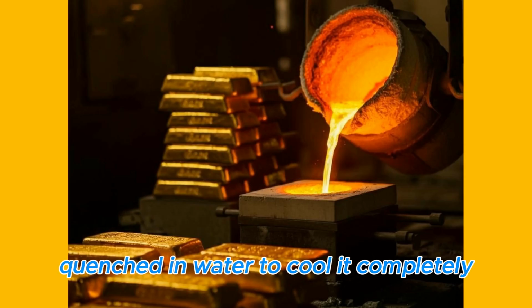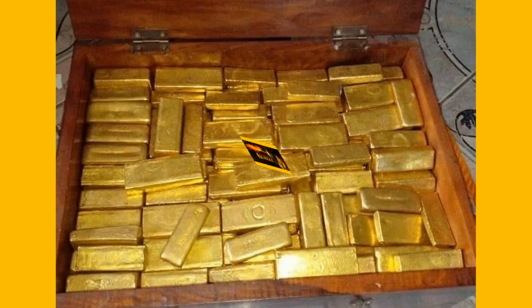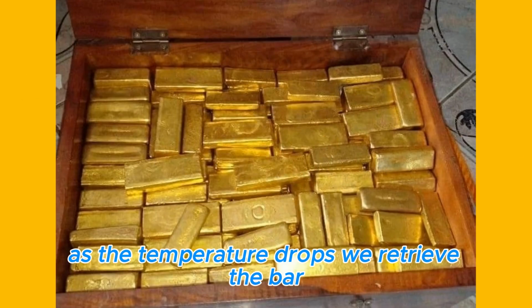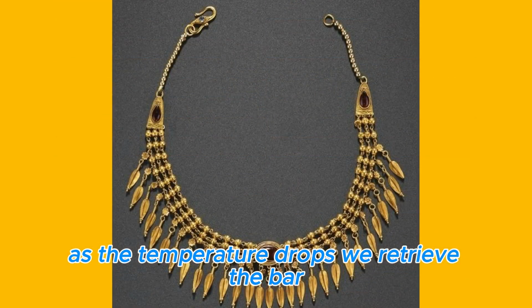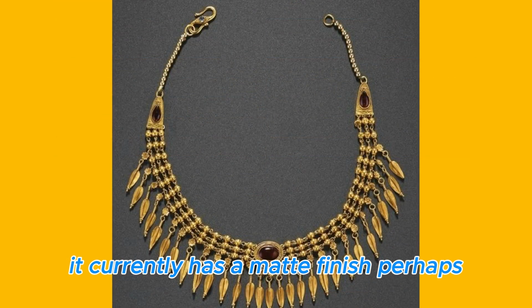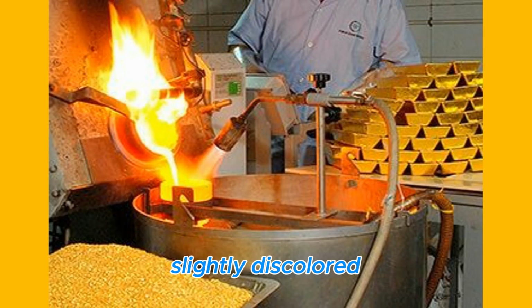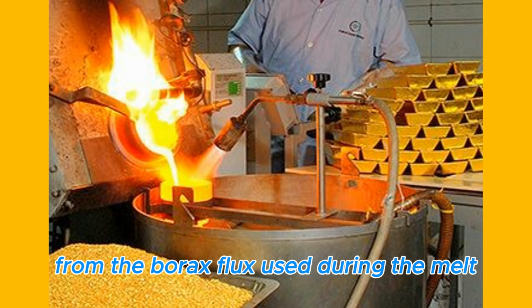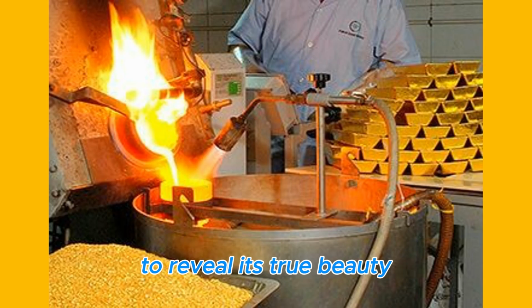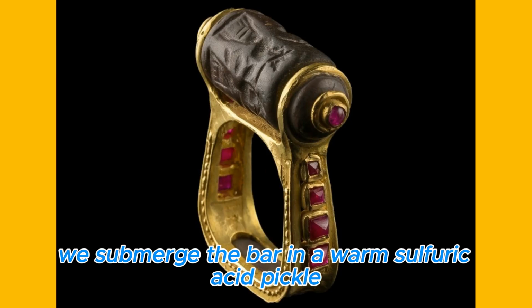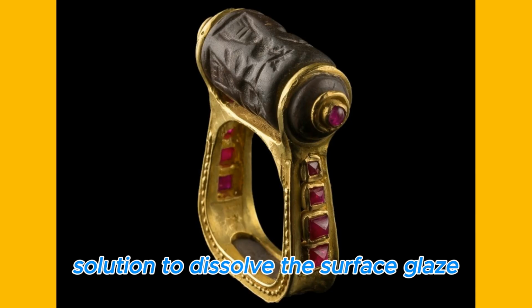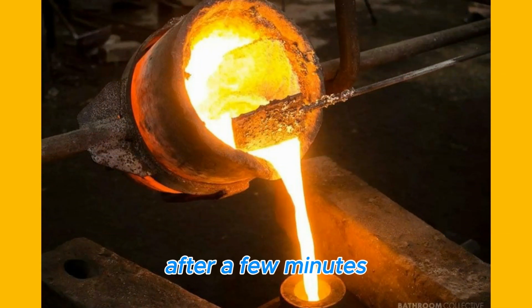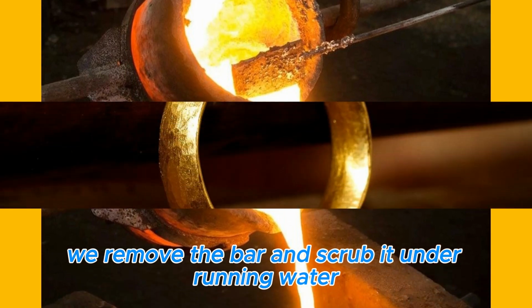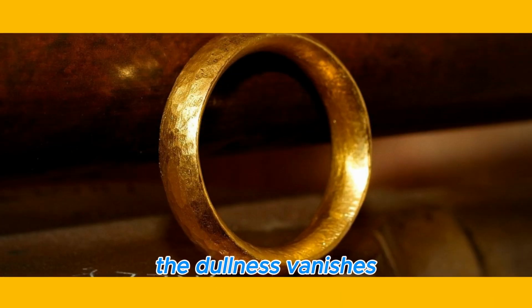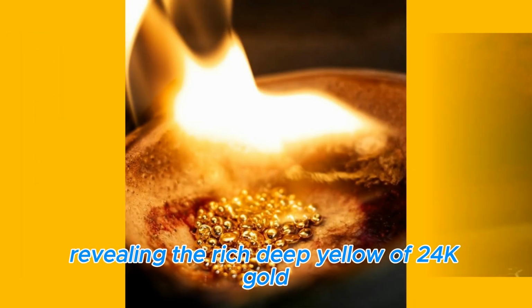It is immediately quenched in water to cool it completely, producing a sharp hiss of steam as the temperature drops. We retrieve the bar. It currently has a matte finish, perhaps slightly discolored from the borax flux used during the melt. To reveal its true beauty, we submerge the bar in a warm sulfuric acid pickle solution to dissolve the surface glaze. After a few minutes, we remove the bar and scrub it under running water. The dullness vanishes, revealing the rich, deep yellow of 24K gold.